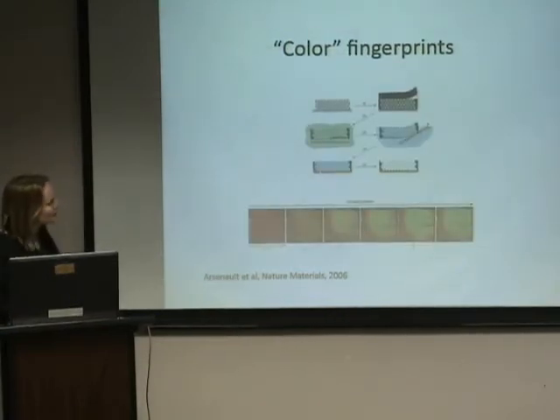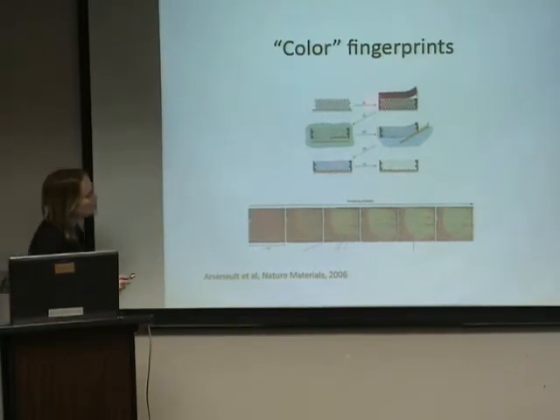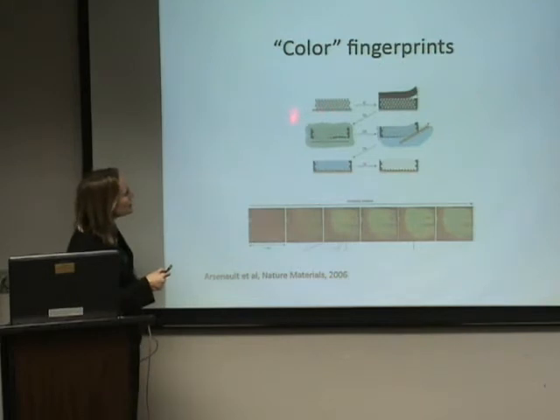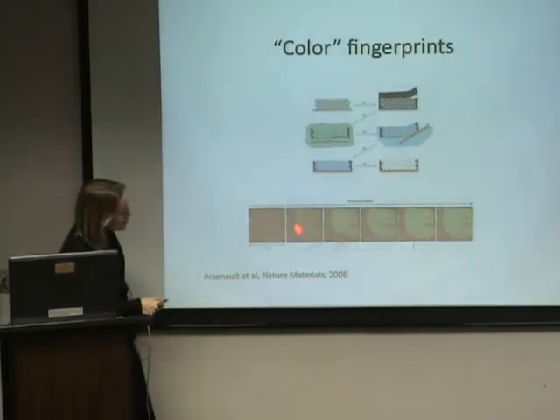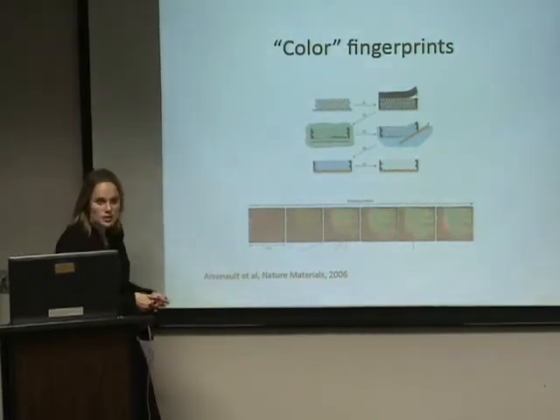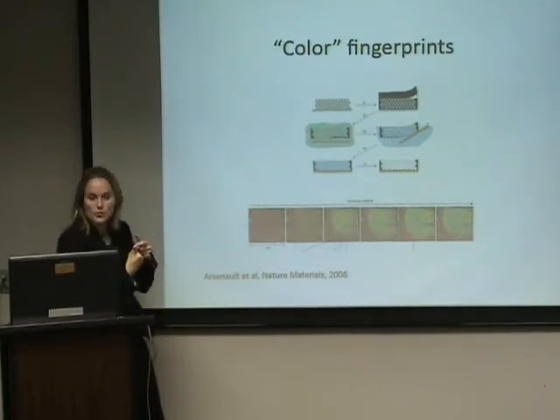In that same paper, they had a nifty demonstration. Up top here, this is how they actually made it. They took some spheres, you self-assemble them so they stack up on their own. Then you infiltrate a background material, peel it off, and then your peeled off thing eventually gets put on the substrate you're testing. And in the end, there's air here in the voids. So they did this kind of cool experiment. They took a thumb. You shine light, say, from the back, and you put your thumb down on the top. As you press down, you see these color changes, and they correspond to the ridges of your thumb. So anywhere that was more pressure.